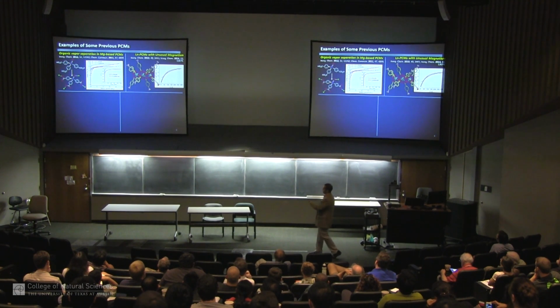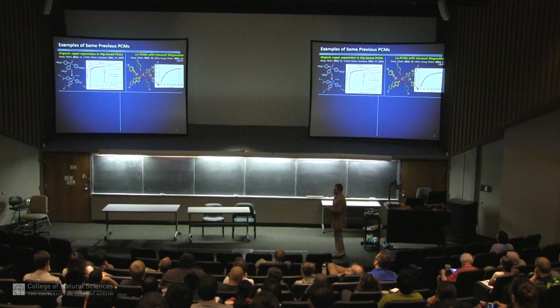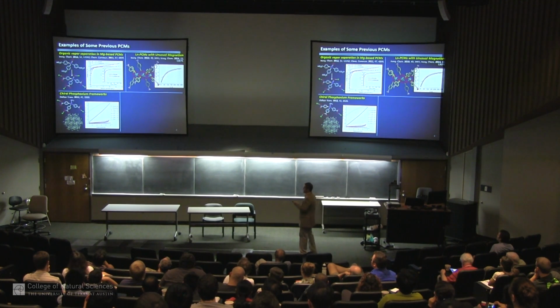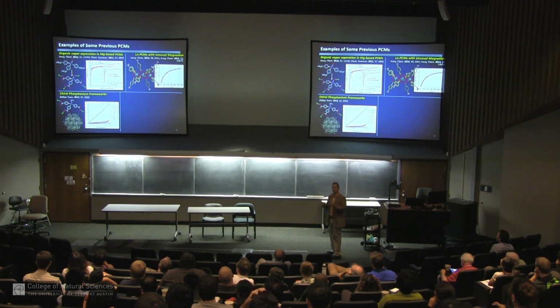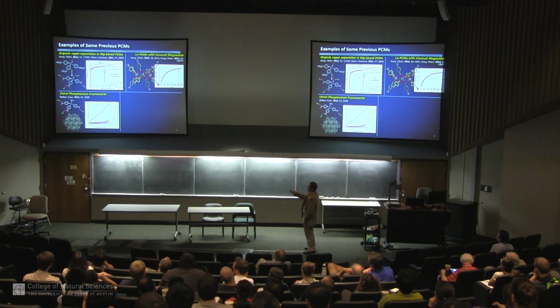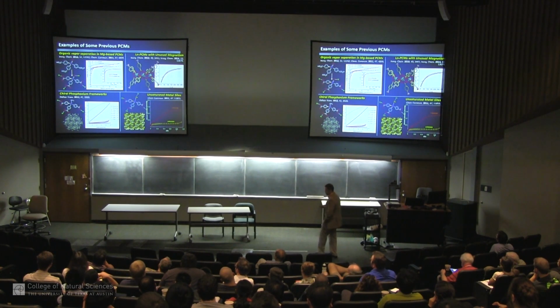We were interested in studying the solid-state magnetic behavior of these materials, and they're very useful as models. We can make chiral materials, which is more unusual in the metal organic framework field, and we can do this by making our phosphine chiral. Remember, all these examples I'm showing you are because we're using phosphine and because we're not just taking a regular ligand from the catalog. So this is how we can get at these materials. This one separates CO2 from all these other gases. And this is really where we want to go.